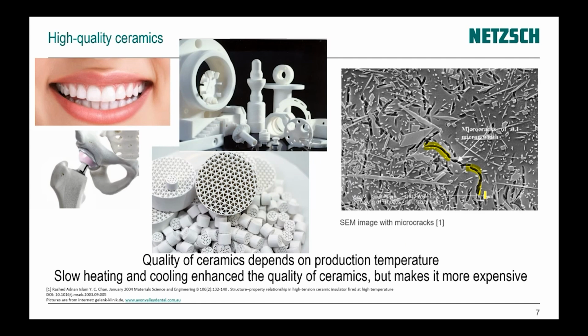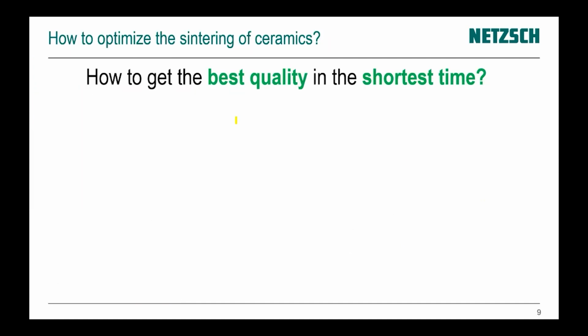If we make the heating very fast, then there are some temperature gradients inside and the shrinkage is not uniform, and therefore there are mechanical stresses and the quality could be decreased. So there should be some kind of optimal temperature program in order to get the best quality in the shortest time. It must be as good as possible, but as short as possible, because for the longest time the quality will be good, but it will be at high temperature, very expensive, and sometimes economically not reasonable.